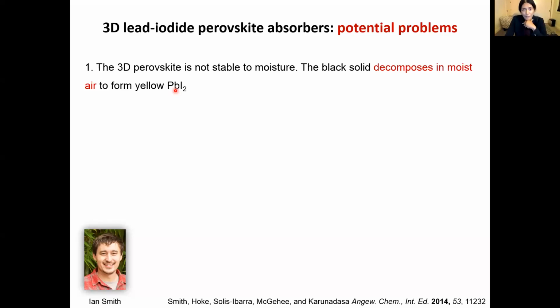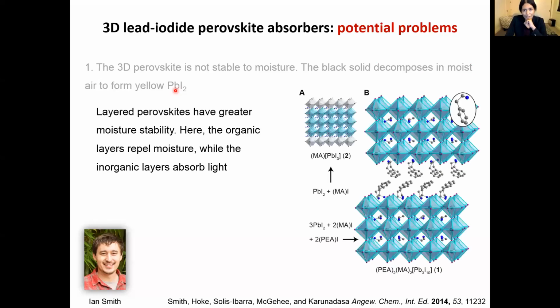So my group showed the first example of a two-dimensional perovskite solar cell, where we found that if you were to form a 2D perovskite with thick inorganic layers, these thick layers that look like we have cut ourselves a very generous slice of my 3D perovskite, these inorganic layers can absorb sunlight and generate current, just like a 3-dimensional perovskite. But now we have this additional layer, this organic layer, that repels moisture. So it's almost like we have taken a 3D perovskite, sliced it, and coated it with something that repels moisture. So these materials are much more moisture stable. We can form perovskite solar cells just out under ambient conditions.